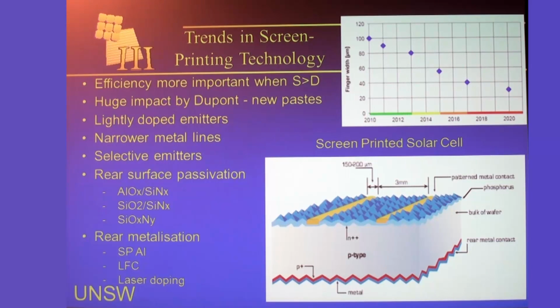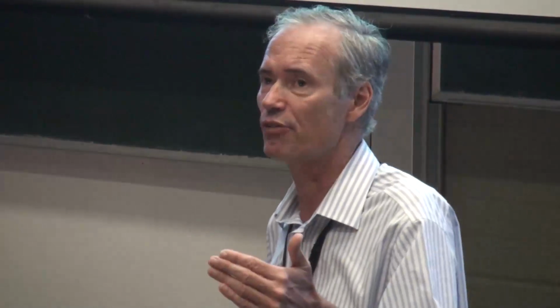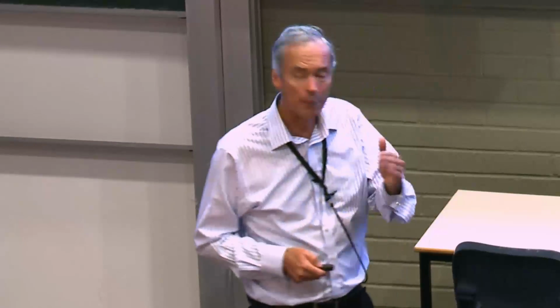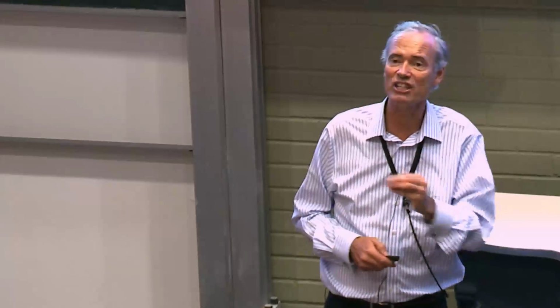And on the assumption that those voltages are achievable, then the team of experts that concluded P-type Czochralski would never get above about 20% efficiency, you have to rethink all of that. Because if those boron-oxygen defects can be passivated in that way, which we now think is possible, it means that 20% is no longer the ceiling for P-type Czochralski, but rather 23% efficiency. It has that big a difference. So that's something that will be very interesting over the next 5 years to see which direction the industry heads. And I'll come back to that again briefly when I talk about N-type technology.